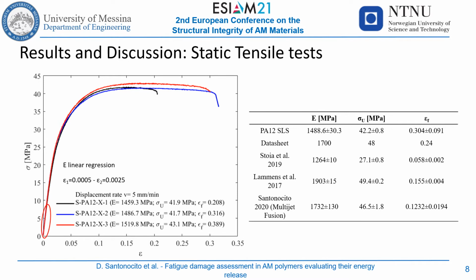To evaluate the Young modulus, the linear regression of the stress versus strain between the indicated strain values has been performed. As it's possible to see in the table, the evaluated Young moduli are lower compared to the value of the material datasheet. The specimens exhibit an ultimate tensile strength lower compared to the value of 48 MPa reported in the datasheet. On the other hand, the elongation at break is higher compared to the nominal value of 0.24.